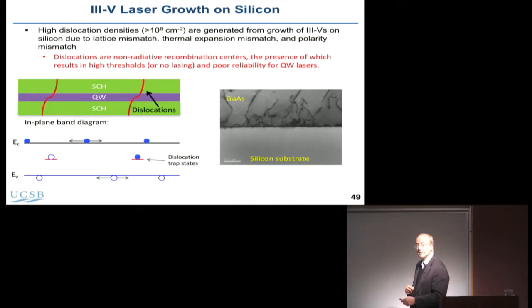This is the reason we're using quantum dots. When you grow gallium arsenide on silicon, there's some dislocation density due to the lattice mismatch. As you go further up, the dislocation density drops. If you put in strained superlattice layers, you can reduce that. But the problem is that the dislocation density is typically 10^8 per square centimeter, which means there's a dislocation every micron. And the problem is the diffusion length in the quantum well is a micron.